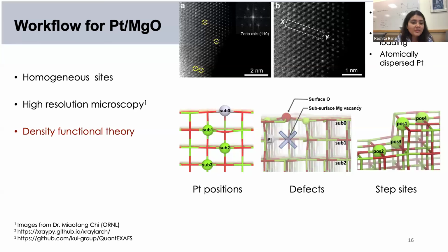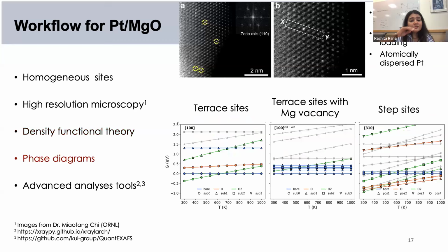So we used an enumeration method where we accounted for all the platinum positions that we could plausibly think of that could be present in our system. We accounted for defects within the system and also adsorbates. And then we also tried to account for both the terrace sites and the step sites. The next step was to see how thermodynamically stable the material was. So we calculated the phase diagrams for all the facets that we had within the database to understand which would be the most stable structures. And then we used QuantEXAFS to run through and see how the fit would work.